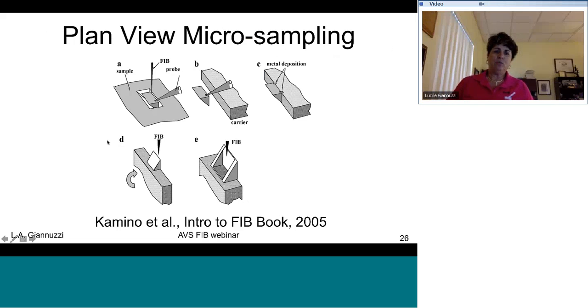Okay, to do plan view work, you have to somehow get your plane of interest parallel to your grid so that you can subsequently FIB mill then parallel to the grid as well. So in this case, the carrier or the grid has been put inside of the FIB and tilted at 90 degrees compared to the normal orientation. And so here, lifted out sort of a chunk of material, FIB milled a chunk of material, and then attach the needle to the sample using the deposition capabilities. Attach this sample to the carrier with the carrier tilted over 90 degrees. There's your deposition. You've removed the probe away.